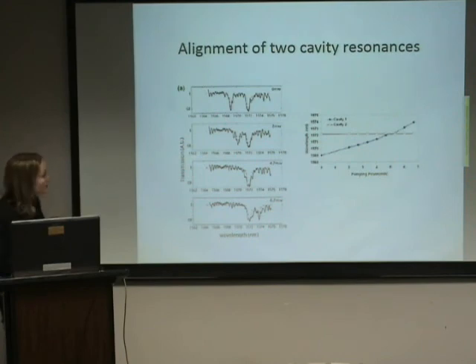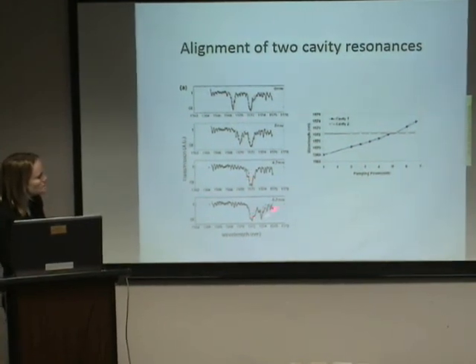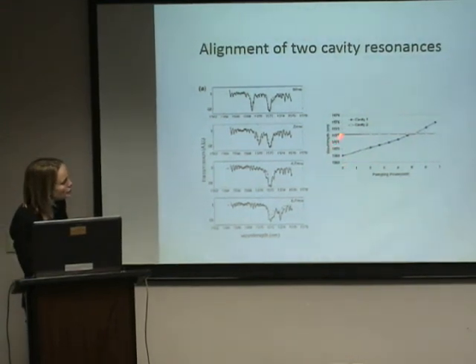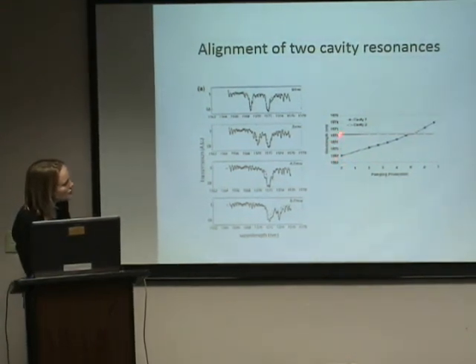We were also able to take a structure where you had two cavities that were initially different, and then take a laser and make those two cavities go together. Here, this is a transmission dip. So you scan wavelength, you see transmission features, and we can bring the resonances together. This here is showing that you can make the resonances cross. So if this is one resonance position, you make the other one move through.